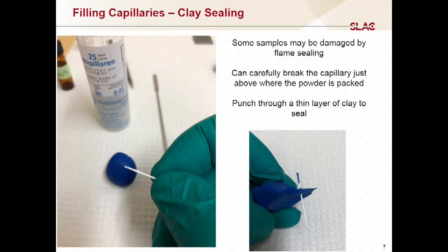Okay, so the other option then is to do clay sealing, and I actually very rarely do this, and so this was one of my first attempts. But basically, here's the capillary, and I've just broken the capillary. And it turns out you want to be kind of careful when you do this because the capillaries are quite fragile, and so it's easy to sort of get a lot of cracks along the length after you do this.